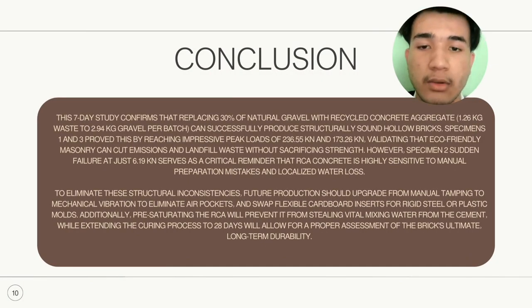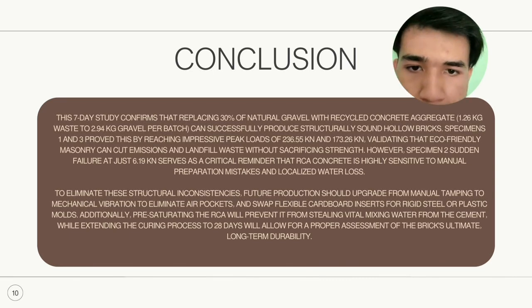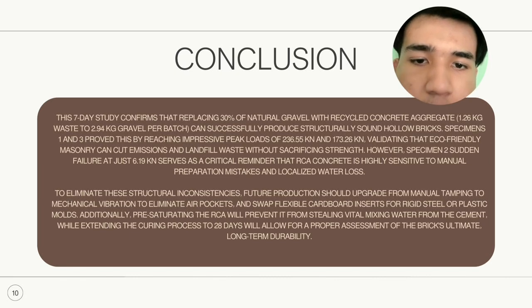So then, in conclusion, we know that after this 7-day study of replacing 30% of natural coarse gravel or coarse aggregate with RCA, we can successfully produce structurally sound hollow bricks. Specimens 1 and 3 prove this by reaching impressive peak loads of 236.55 kilonewtons and 173.26 kilonewtons, validating that eco-friendly materials can cut emissions and landfill waste without sacrificing strength.